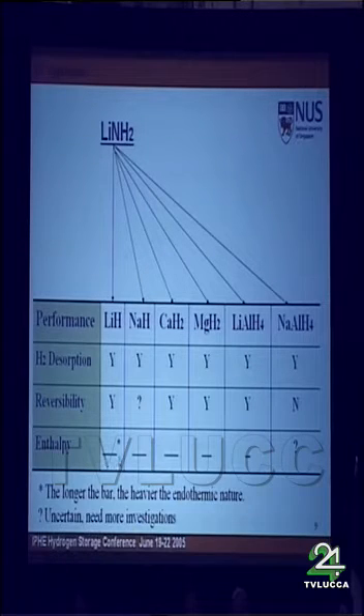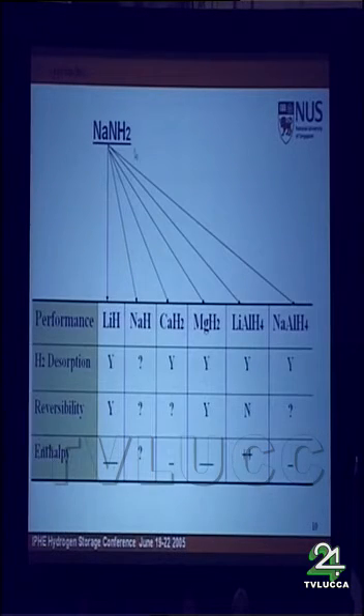The longer the bar means the more heat required for the hydrogen desorption. You can see from these few chemical reactions that the endothermic properties change, and some of them exhibit quite good endothermic values. We can also use sodium amide and change the hydride. We've got a variety of systems which also give hydrogen and also show certain reversibility. One of the interesting features is that when we react sodium amide with lithium alanate, we found a kind of exothermic reaction. I will touch on this reaction in later slides.